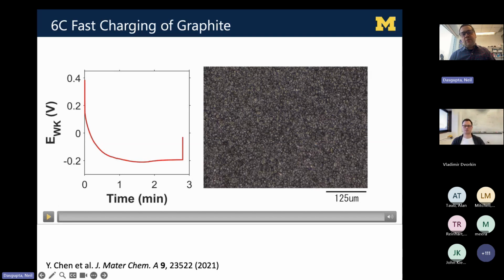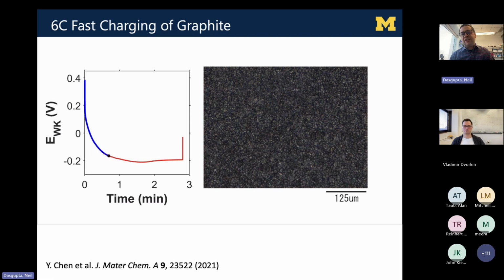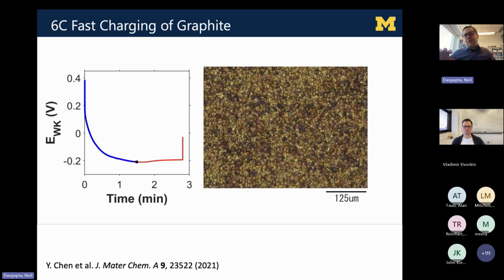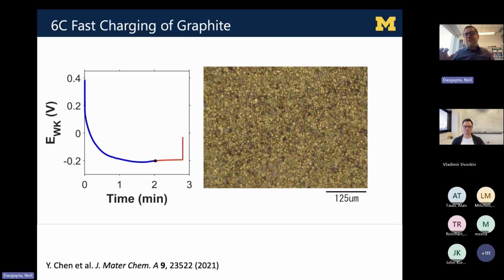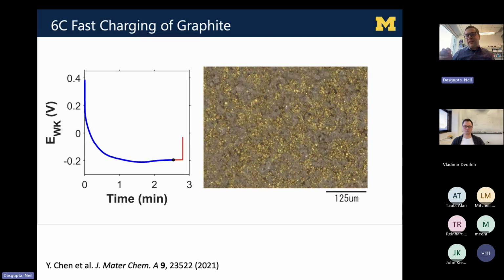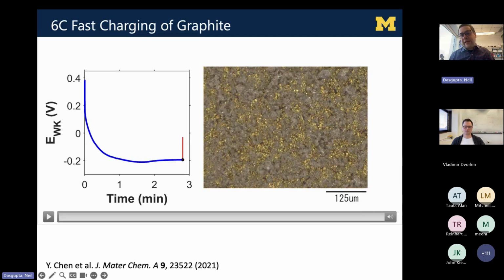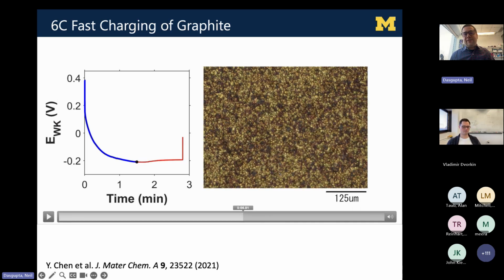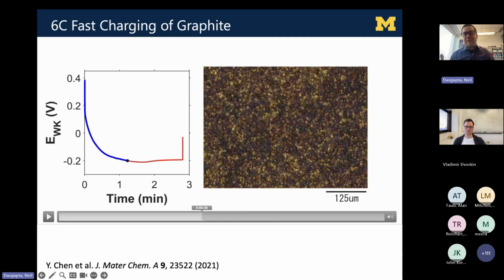And as I play the video, what you'll see is that the color change in the graphite looks very different under fast charging conditions. We can see that not all the particles turn gold at the same time. Some of them start to lithiate much faster than others. And we can also start to visualize this deleterious lithium plating event that occurs onto the surface. So if I flip back, you can see one of my favorite pictures we've ever taken in our optical microscope.